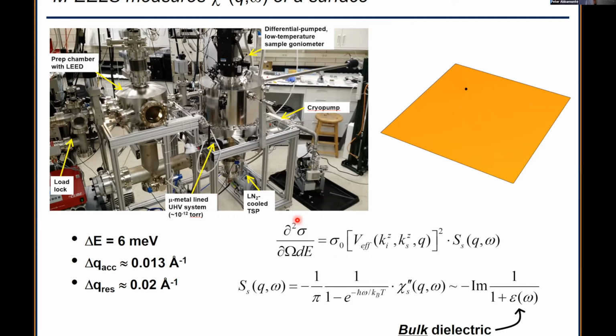So the differential scattering cross section is some matrix elements times S of Q and omega, which is the surface density correlation function. The disadvantage of this technique is that it is a surface probe like photoemission or STM. The advantage is it actually measures the response function that we need. So this density response is actually a Bose factor times chi double prime of the surface. So there's a conversation to be had over what response function this is.